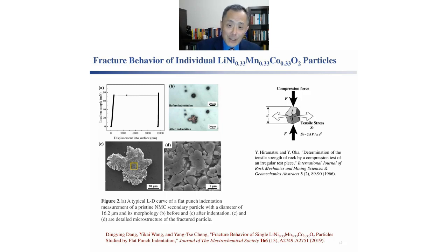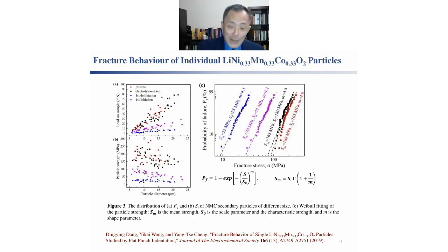Since fracture is statistical in nature, the student performed, again, a very large number of measurements, and then she used the Weibull statistics to extract the average strength of the particles: the fresh particles, particles after first lithiation, particles after first delithiation, as well as the possible influence of the electrolyte. And we learned that immersing the particles in the electrolyte did not affect the strength of the particles, but with just one lithiation and delithiation cycle, the strength can change significantly.